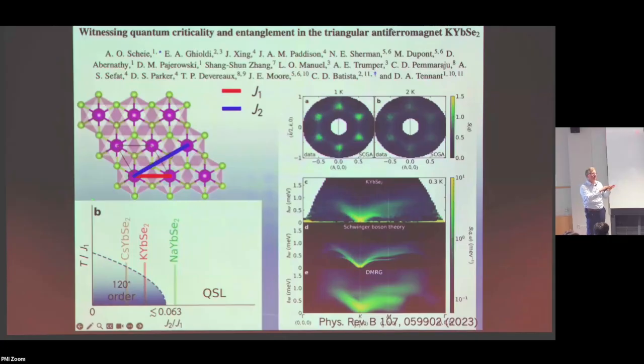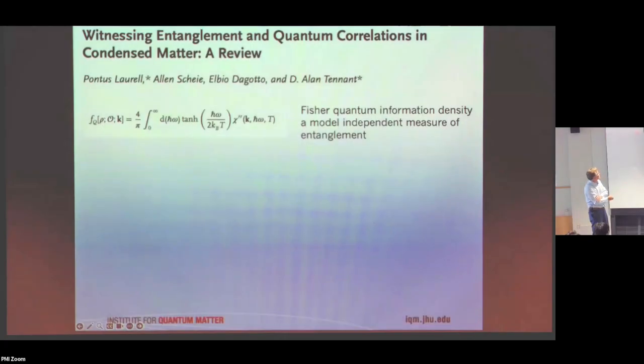This thing does have a magnetic order eventually, but it has no spin wave excitations. And the magnetic order is something that influences things at really low energies. But all of this other part of the excitation spectrum is really the characteristic excitations of this J1, J2 quantum spin liquid. And so they've been looking with Schwinger boson theory and DMRG to try to calculate that and have a pretty good agreement between the experiment and some of the theory.